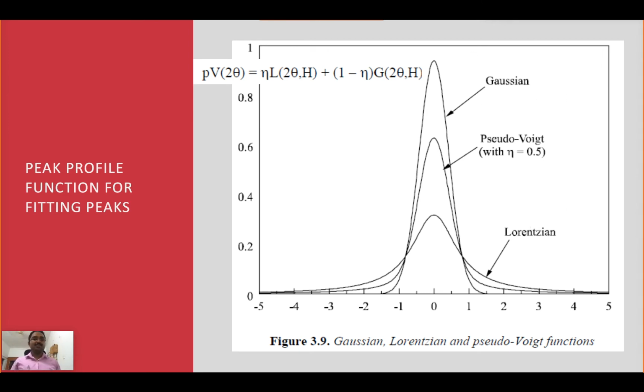So now we have a solution here. We have the Voigt function, which is partly Lorentzian, partly Gaussian. For example, if I take eta to be 0, this becomes completely Gaussian. If I take eta to be 1, what will happen? G is lost, we have completely Lorentzian. So the Voigt function is nothing but a combination of Gaussian and Lorentzian. Eta can be from 0 to 1. Any value in between means there will be a combination of Gaussian function and Lorentzian function.